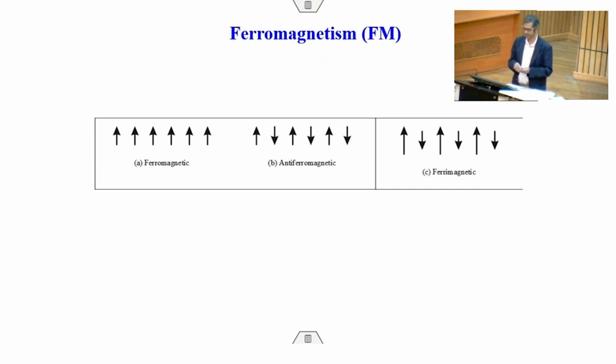Free electrons are like that. Then band theory is able to explain many non-integral values of that. Now, in iron, the 3d electrons are not fully localized, as we discussed. About 5 to 8% have some itinerant character, and those electrons mediate the exchange coupling between the localized moments.